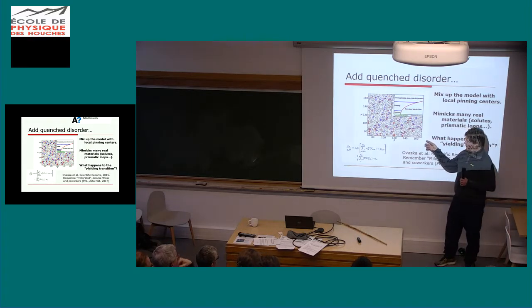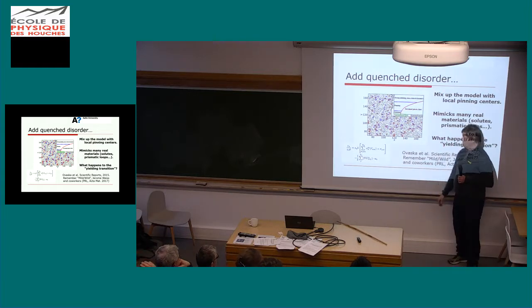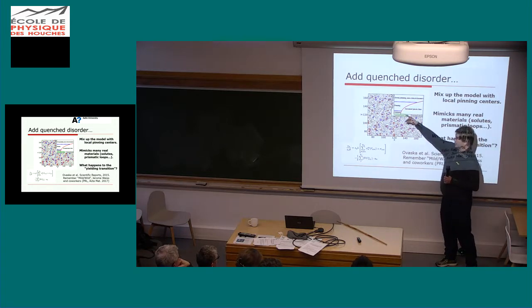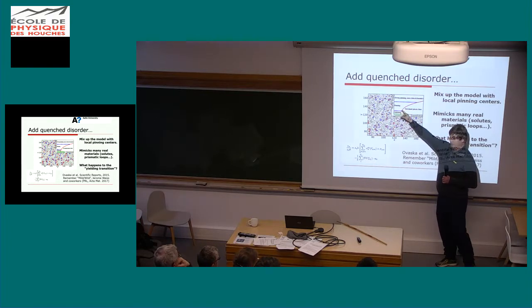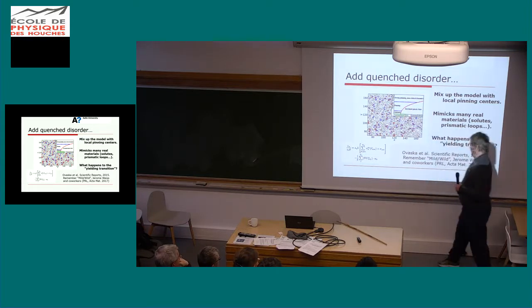As you would simulate it, these points are the solute atoms. This is 2D, but you can, as you will discover, do this in 3 dimensions. You get the phase diagram really saying that if I'm at low enough stresses, disorder is not relevant; at intermediate values, you get a real phase transition; and then if you add enough of that, you kill it all.